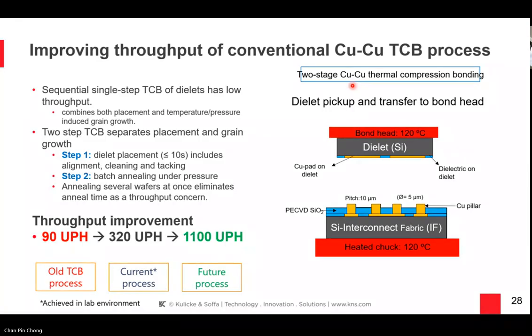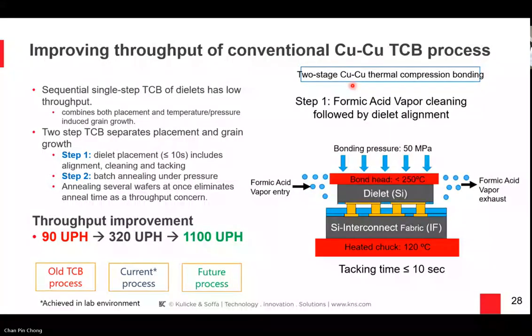Here is where we actually introduce the formic acid. The formic acid will then reduce the surface oxide completely, and then we do an alignment step, which is a second order alignment. Then we bring the die down and quickly heat it up to about 250 Celsius and apply a bonding pressure of about 50 megapascals.